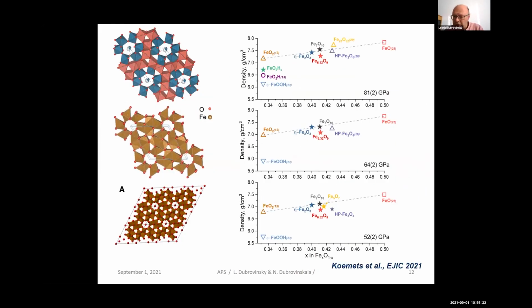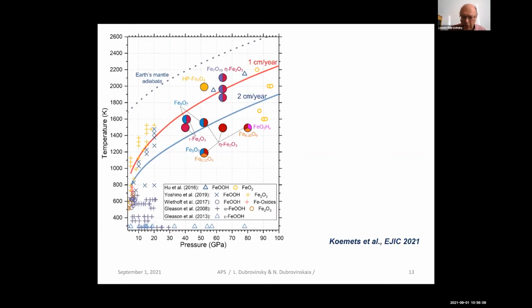Okay, so as soon as we have a structure, as soon as we have a chemical composition determined from the single crystal diffraction, we can determine the densities, and we can look at how these densities fall along the different compositions of iron oxide or hydroxide. And as you can see, in all studied pressures from 50 to over 80 GPa, our data show that if there is some amount of hydrogen in this phase, it is very small. It is highly unlikely. Okay, so summarizing our observations on this system, on the behavior of Fe-O-H.